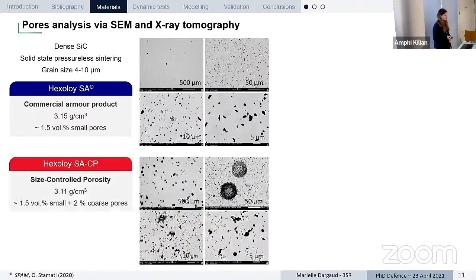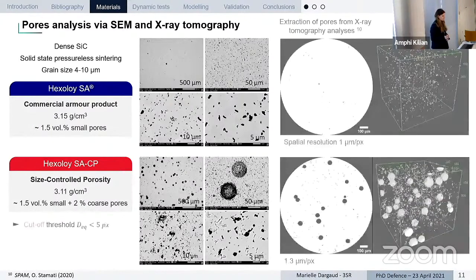And the second material is a derivation of this material where we have about the same microstructure, but there are some very large and spherical pores in this material. For this reason, we are going to call this material Hexoloy SA-CP, CP for size-controlled porosity. These pores represent about 2% in volume.